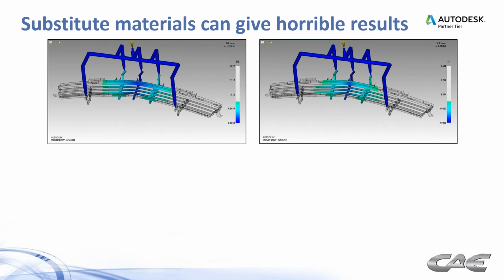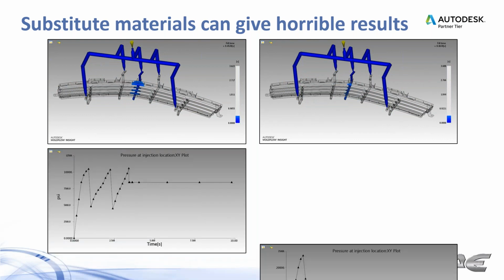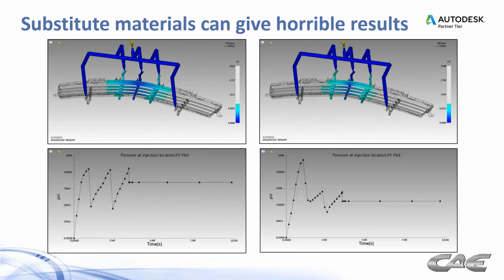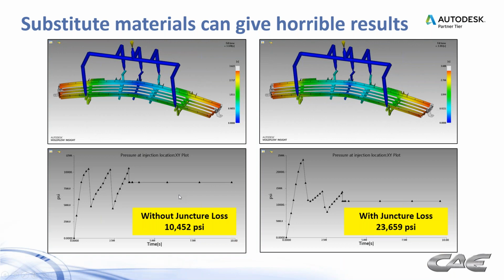I preach this in just about everything I do, Moldflow wise, but make sure that any materials that you're using are well characterized before they're being simulated on your mold. In this case, we're showing the exact same setup in two cases. In one case, we have material without juncture loss data. In the other case, we have it with juncture loss data. And you can see the difference in the pressure predictions, okay? And this is just in a standard part. If you go to thin parts, this becomes amplified pretty quickly.